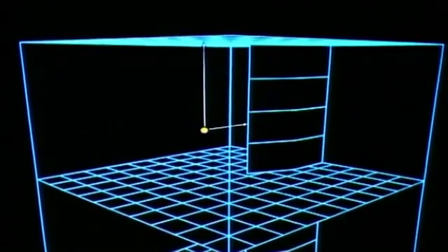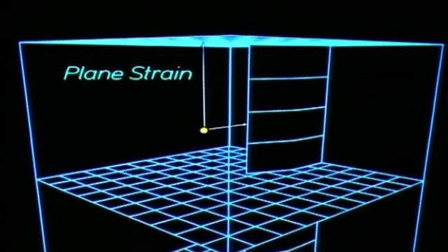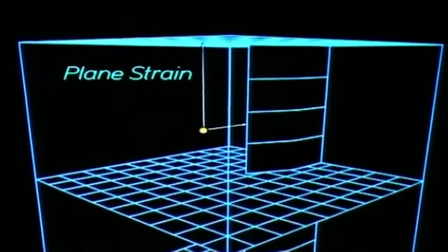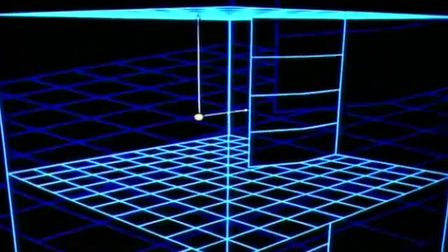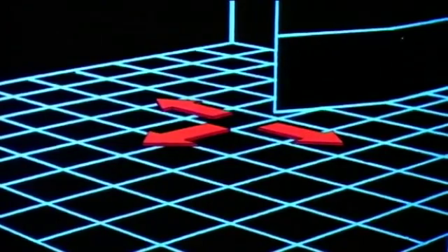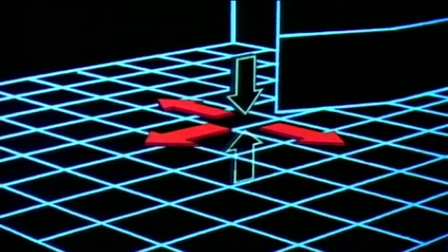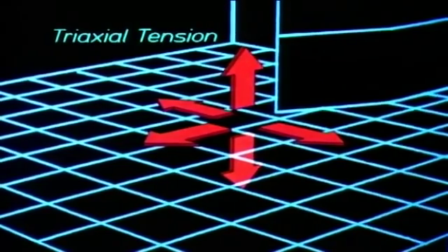This point will then be in plane strain, as the distance along the crack front between the specimen edges is much greater than our distance from the crack tip. In plane strain, there is no strain parallel to the crack tip. Although near the crack tip there are large tensile strains, and these would normally cause contractions parallel to the crack because of the Poisson effect, the contractions are constrained by the large amount of surrounding material. This applies in the interior, a long way from the edge, but not at the surface. To prevent this contraction, a tensile stress is set up parallel to the crack border, which, together with the other tensile stresses, gives a state of triaxial tension at the crack tip.